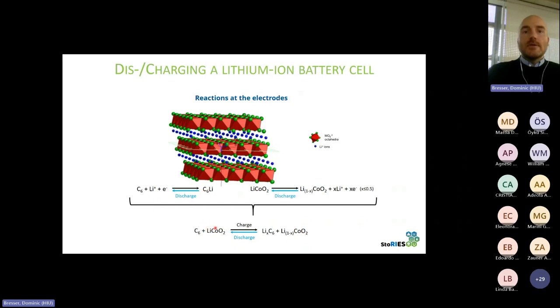You can summarize that upon charge, the empty graphite and the fully filled lithium cobalt oxide react to lithiated, or lithium-intercalated, graphite and lithium cobalt oxide with a reduced amount of lithium in the structure. And upon discharge, exactly the same. This is the nice thing about lithium-ion batteries: you just intercalate and deintercalate lithium cations from two layered structures that undergo few structural changes, limited compared to other classes of materials. This is the reason why this is so reversible, so that we can charge and discharge lithium-ion batteries 1,000 or 2,000 times. And it's the other reason why this in its early stages was called a rocking chair battery, because the lithium cations migrate from one electrode to another, back and forth, back and forth.